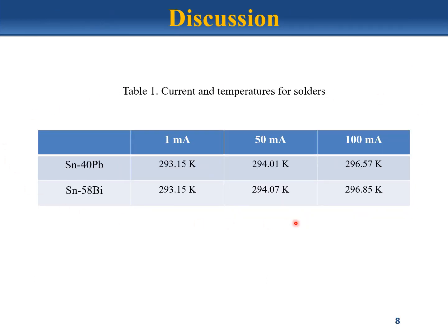So here we can see some additional data points on what temperatures we have observed when running simulations with different amounts of currents running through the structure. We can see that as the current increases, the temperature in the structure also increases. But we can also see that even though the two solder compositions are different, the temperature caused by the current is roughly the same.